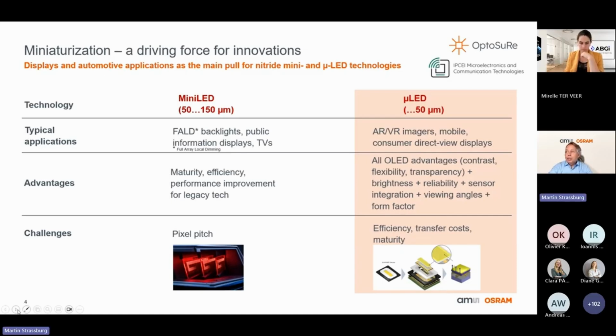Still, we have the challenge of the efficiency that comes with the dimension. Here we have really the problem that with having such small dimensions, we come into the lengths where the diffusion lengths of carriers play a role. In semiconductors, the diffusion lengths are between 1 micrometer and up to 20 micrometers. And now you can really see where the problem occurs. When we have a dimension of the chip of less than 10 micrometers, each carrier can easily come to the surface. And as a physicist, I can say the biggest defect of the crystal or the semiconductor wafer is the surface. And that is where we would have a non-radiative recombination. The non-radiative recombination yields exactly a loss, and we would lose efficiency.